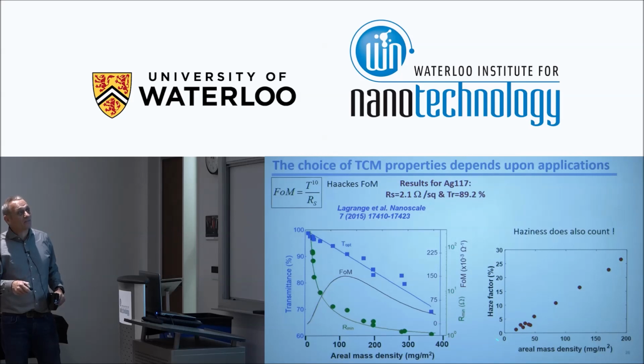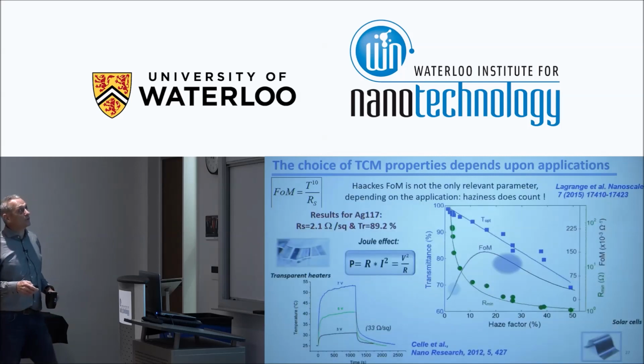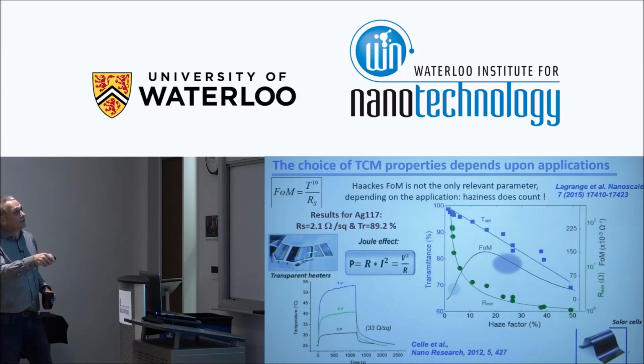And that means for some applications, like for a display application, you want to have a very low haze factor, often lower than 3%. But if you want to work with solar cells, for example, you're happy to have a large haze factor. So it's not only this theoretical figure of merit, but it's application dependent. And for example, if you want to work with displays, or for transparent heaters, it's better to work here at low haze factor. But if you want to work with solar cells, it's better to work with a larger area density, because you want to have a larger haze factor.